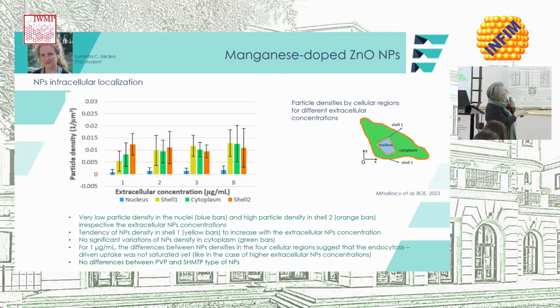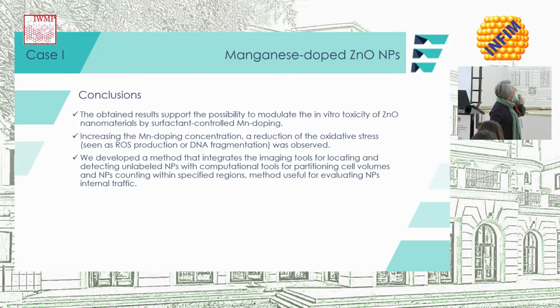For the smallest concentration that we used, 1 microgram per ml nanoparticle, the differences between the nanoparticle densities in the 4 regions, you can see here, are suggesting an endocytosis-driven uptake, which, for this concentration, is not saturated yet. But for higher concentrations, this phenomenon seems to have already reached saturation. There were no differences between the 2 types of nanoparticles in terms of surfactant. Okay, so we obtained these results, which we used very fast.